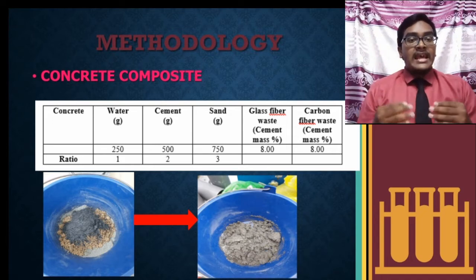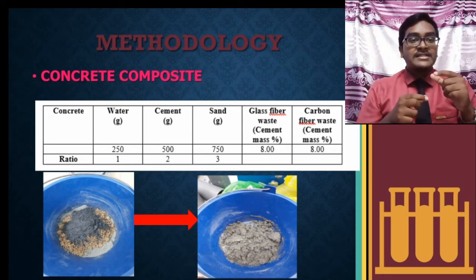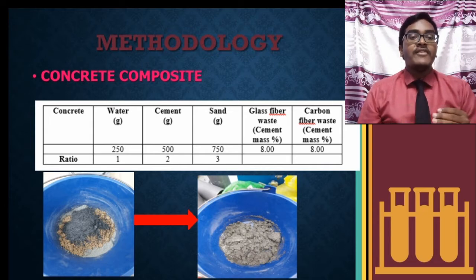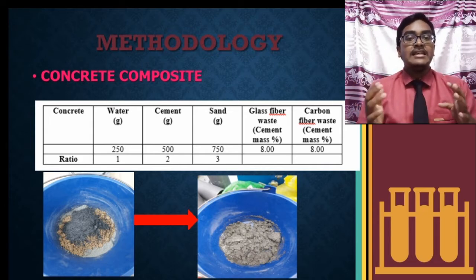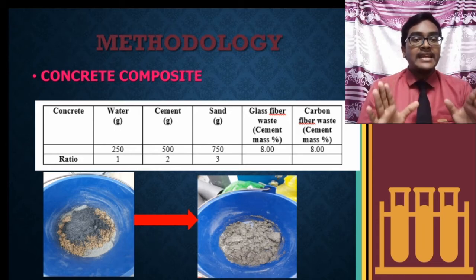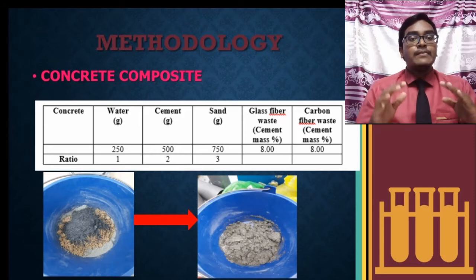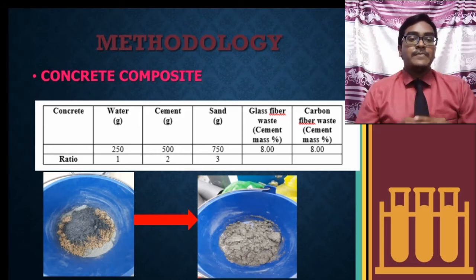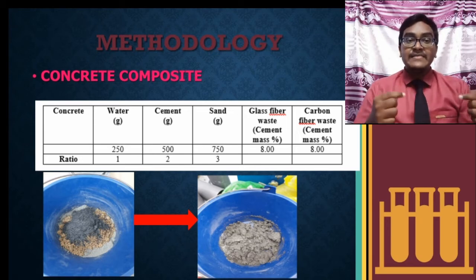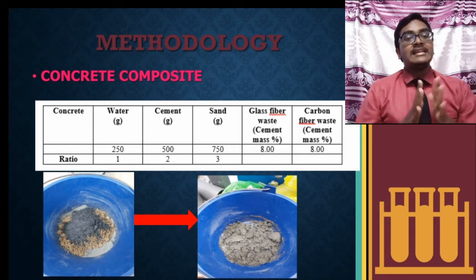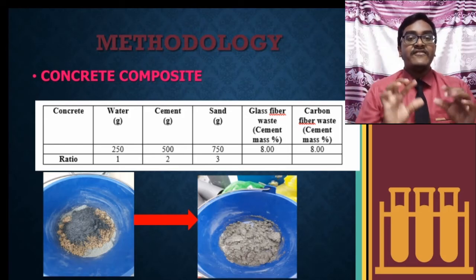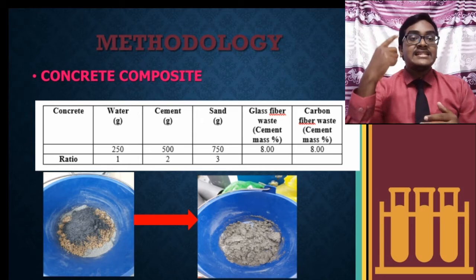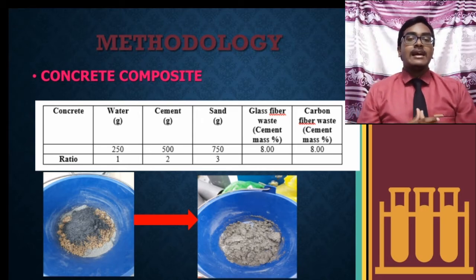Then pour the normal concrete into a cylinder-shaped mold measuring a diameter of 100 mm and height of 150 mm to keep the concrete in place until it has set, and push it so that it fills the space. Pour the concrete with recycled glass fiber into a cylinder-shaped mold measuring a diameter of 100 mm and height of 150 mm to keep the concrete in place until it has set, and push it so that it fills the space. Lastly, repeat the same steps for concrete with recycled carbon fiber.